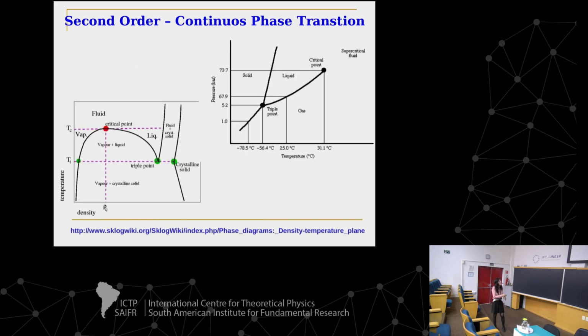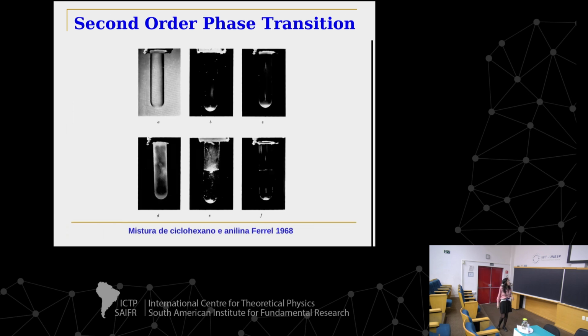But then, let's approach this point, the critical point. Sorry, I didn't mention that I was increasing the temperature at constant pressure in this material, a mixture of cyclohexane and aniline, in a very, very old experiment. What happens is that as you get close to this, you have the two phases, and then you have a moment in which your whole tube becomes blurred. The photo is not very good.